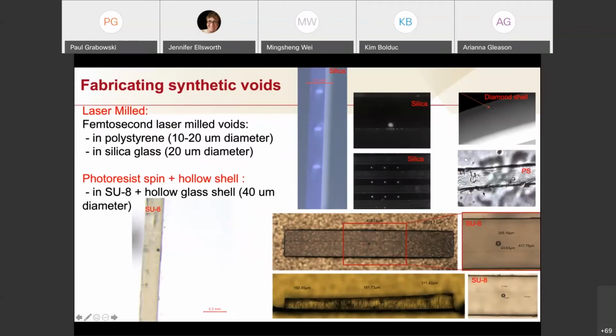Other samples, like the plastics, for instance, we make synthetic voids in them. I also have a test sample, a silica here. It's a bit easier to work with. And so we use femtosecond laser milling to generate pore spaces or voids in the sample.